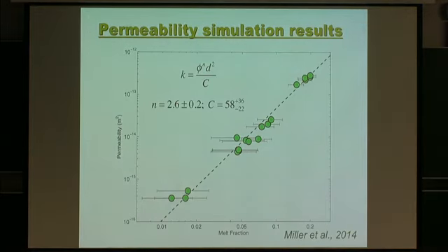And then these are the calculations. So you see that at 20% sample, you have some variations between the regions, and at 10%, 5%, and 2%, you go almost as low as 1%, all right? So each one of these is a calculation. The permeability, because this is computed, there isn't much of an uncertainty to talk about.